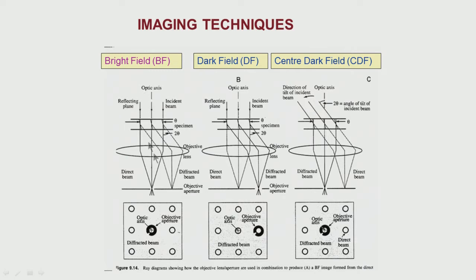When diffraction is taking place from a sample, if we cut off the rays which are scattered in other directions by putting an aperture at the back focal plane, where the diffraction pattern is formed, then only this beam is there, and if you magnify it, we get the image which is called a bright field image. And if you put an aperture around this diffracted beam and get the image, this is equivalent to viewing the sample in this direction of the beam, and in other various directions. Each of these directions gives different information, and that is how we can get complete information about that sample.